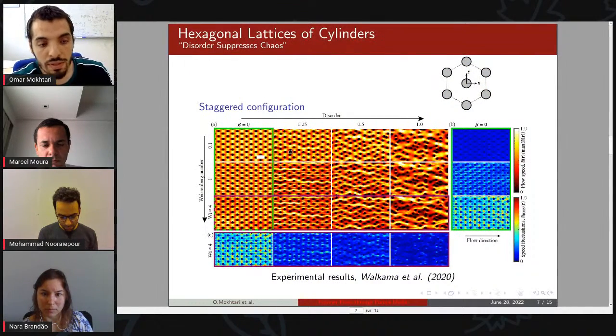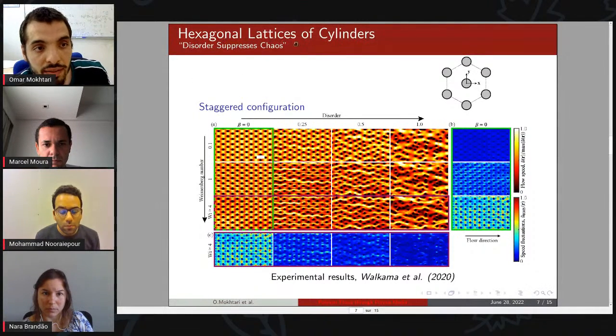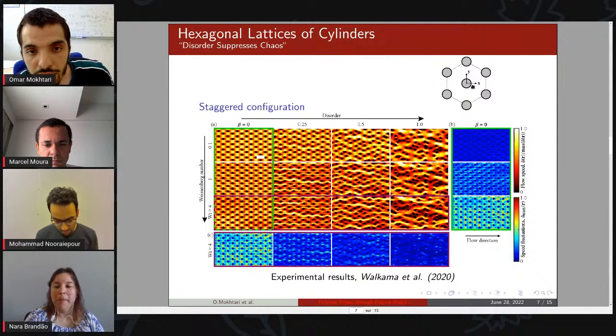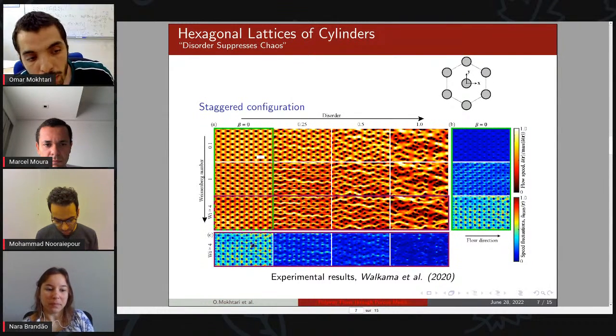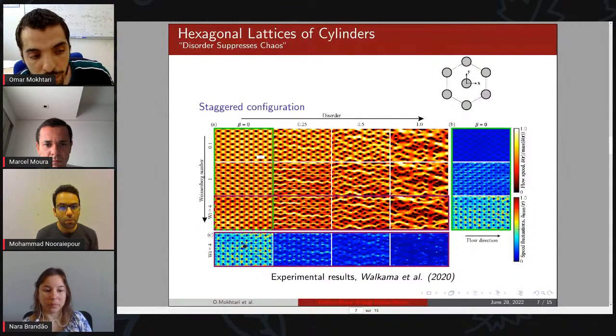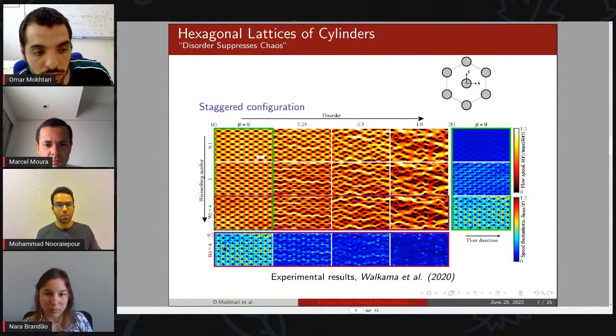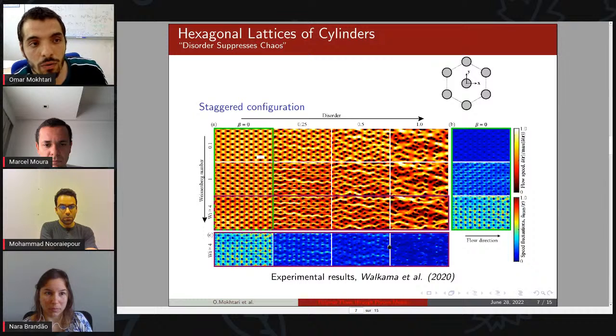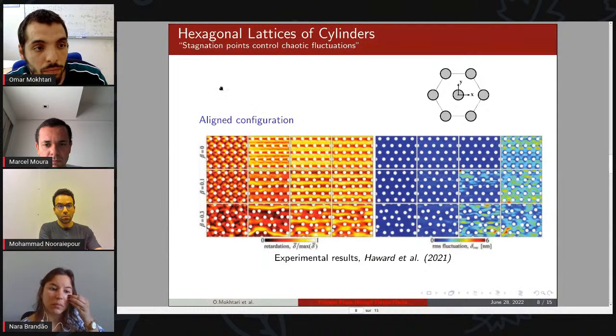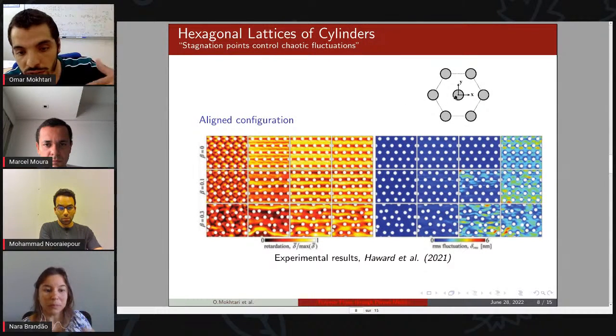There are two very recent experimental results. The first one considers a hexagonal lattice of cylinders in a staggered configuration. By increasing the Weissenberg number, they observe a transition to unsteady flow with velocity fluctuations, and by introducing disorder, the fluctuations disappear. They say that disorder suppresses chaos in viscoelastic flow through porous media. But considering the same geometry, in an aligned configuration which corresponds to a rotation by 30 degrees of the first one,